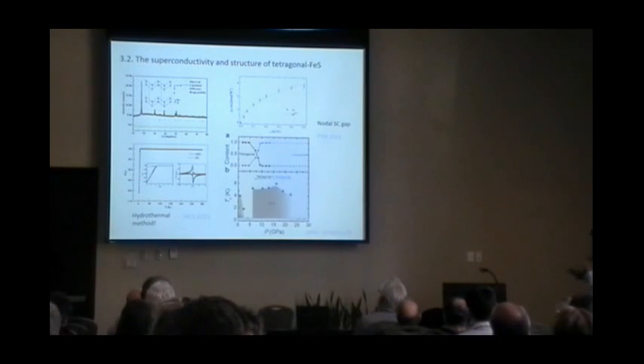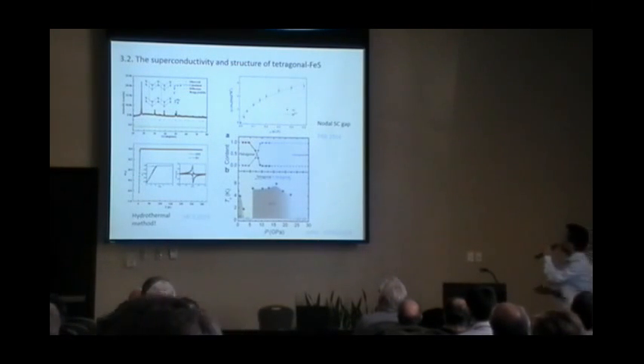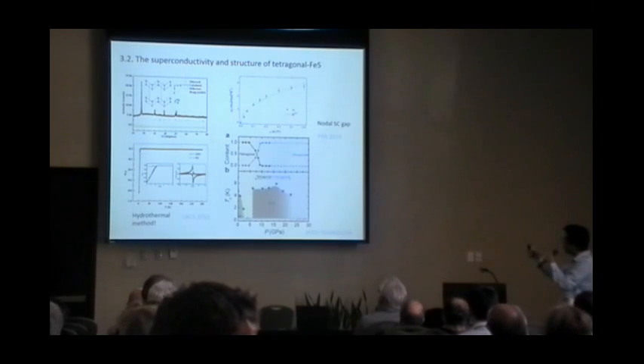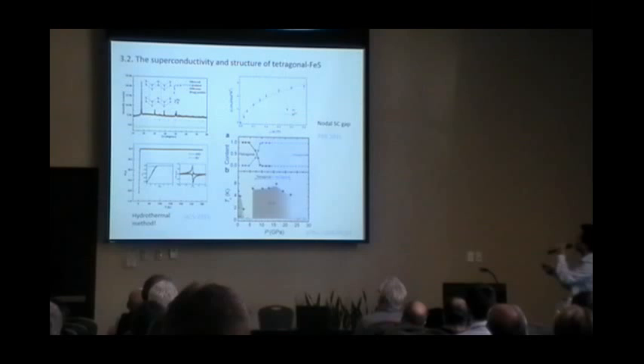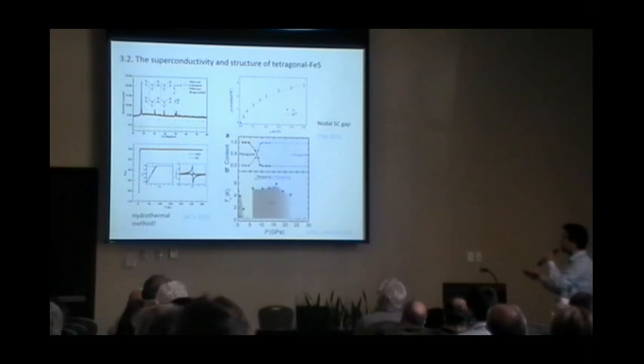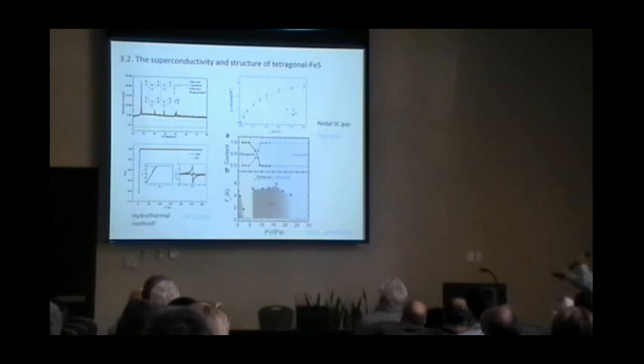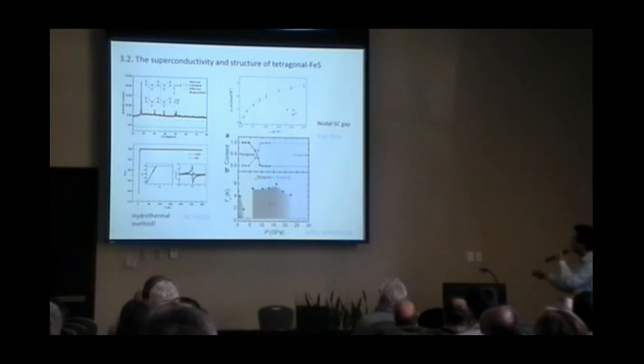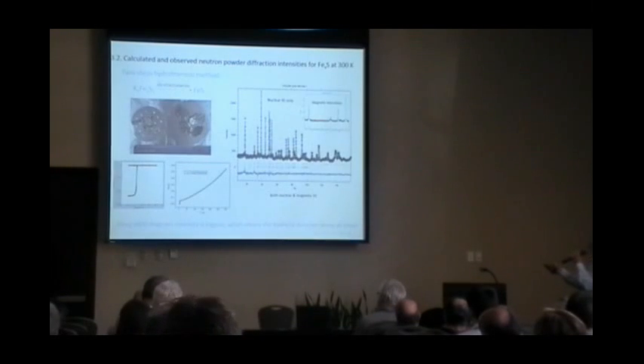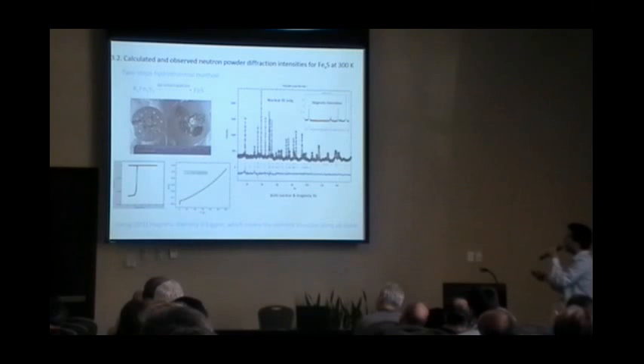Okay, so finally, I want to introduce our new results about the new superconductivity of the iron sulfide. In 2015, a new compound was reported. They used the hydrothermal method to get this phase. There's a new paper showing here. This one also shows the second dome under high pressure. So we use the two-step hydrothermal method. We grow the single crystal of the iron sulfide, so we can see the TC. It's consistent with the previous one.